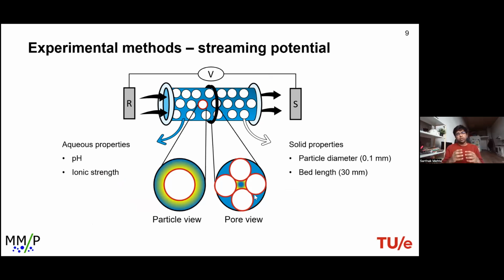What we do is use non-porous silica particles of 0.1 mm diameter and put them in a cylinder of 30 mm length. We close the cylinder with mesh electrodes—on one side we have the reference electrode, on the other side the sensing electrode.